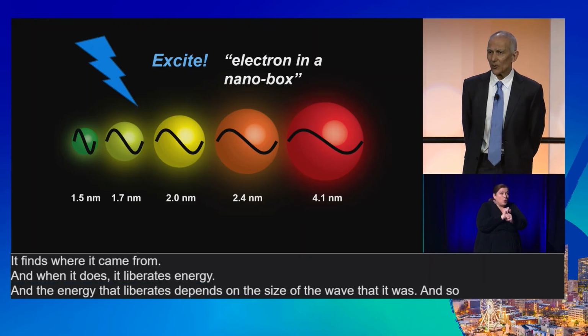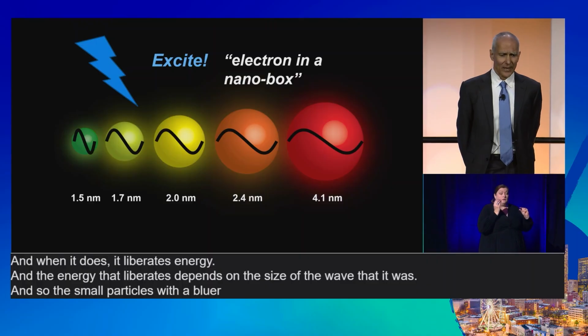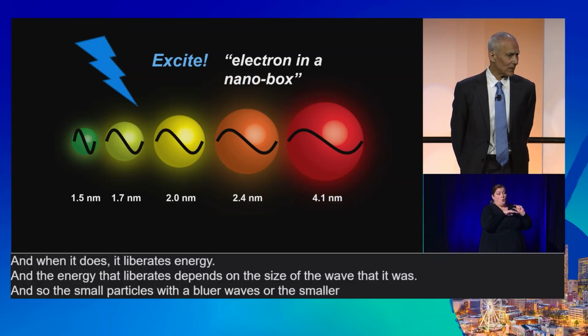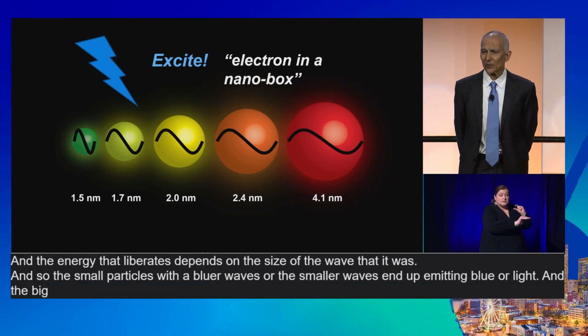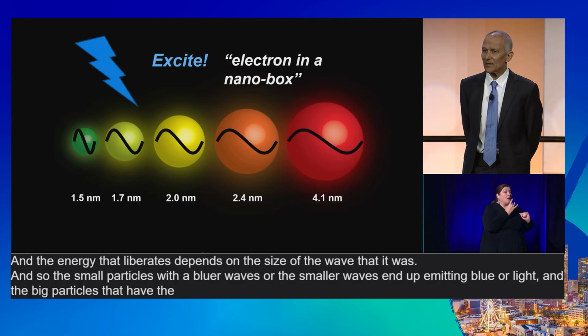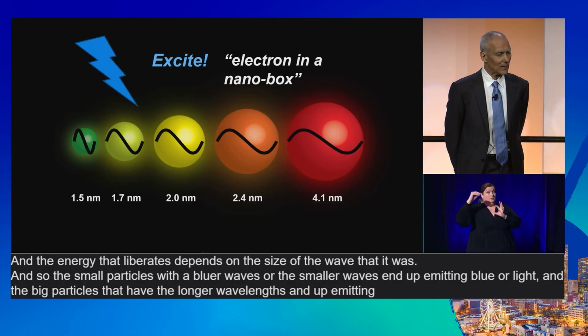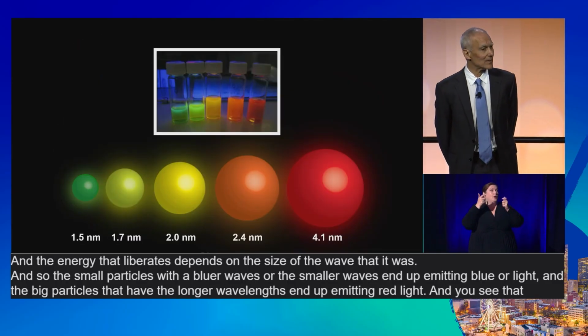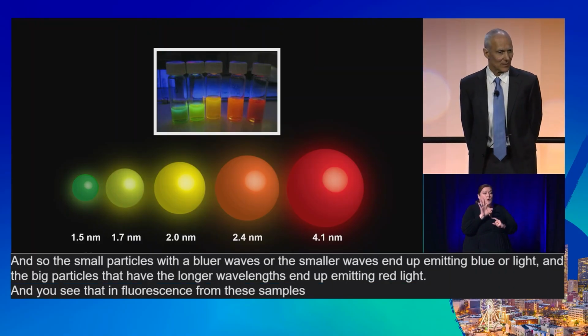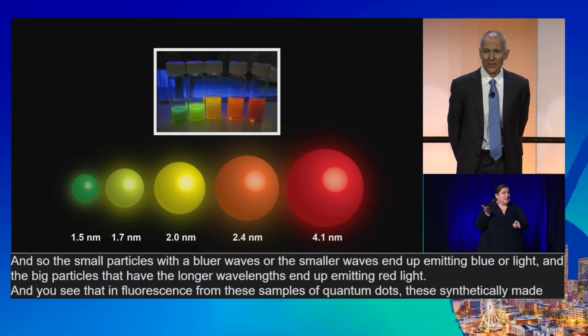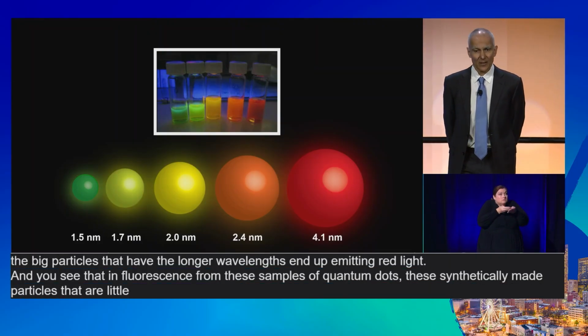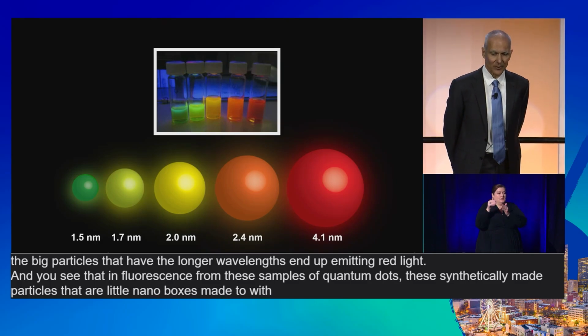And so the small particles with the bluer waves, or the smaller waves, end up emitting bluer light, and the big particles that have the longer wavelengths end up emitting redder light. And you see that in fluorescence from these samples of quantum dots, these synthetically made particles that are little nanoboxes made with one electron in them.